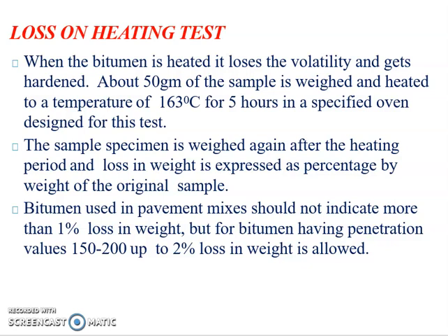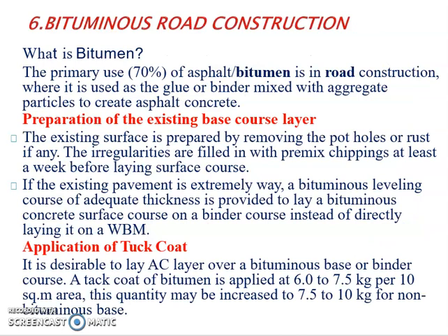The sample specimen is weighed again after the heating period and the loss in weight is expressed as a percentage by weight of the original sample. The bitumen used for pavement mixes should not indicate more than 1% loss of weight. But for bitumen having penetration values 150 to 200, 2% loss in weight is allowed.